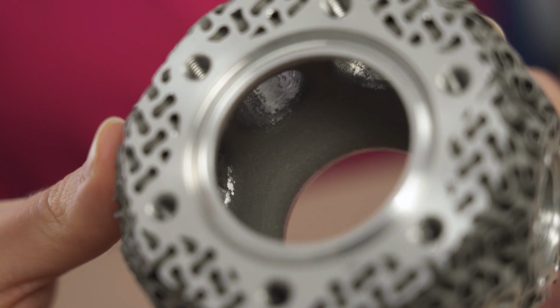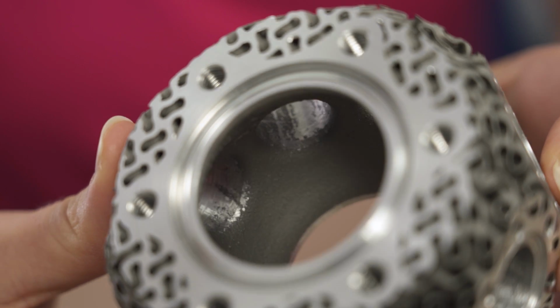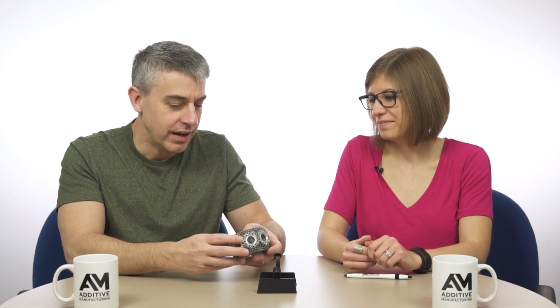So one of which is, if you look at the inside of the chamber, it's still got this rough printed surface. And there were concerns that a rough surface would outgas more than a smooth surface. And so to test that, they left it this way. But they actually found in doing experiments with this that the rough surface performed a lot better than they expected.